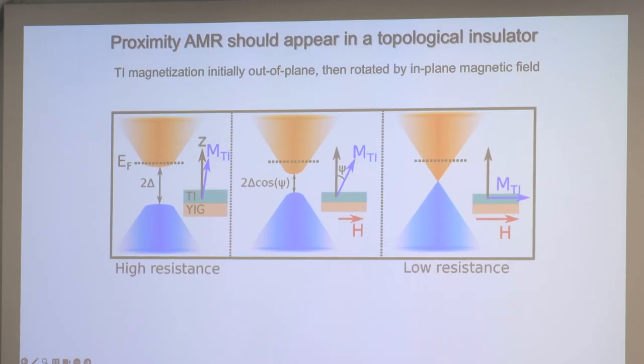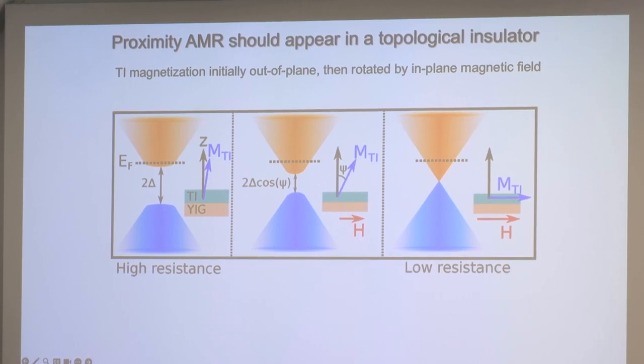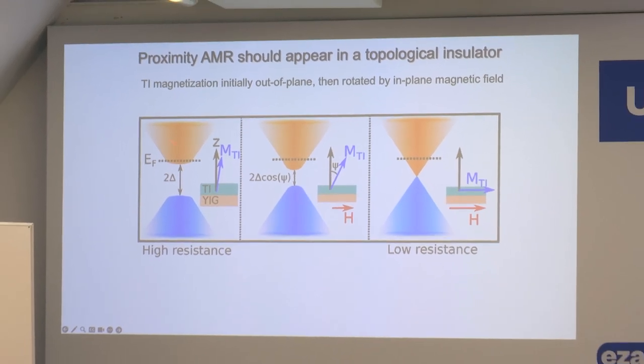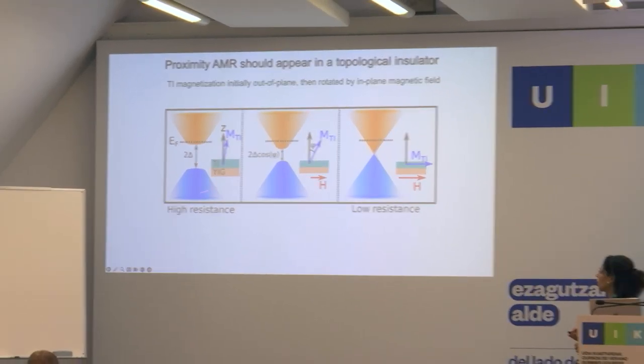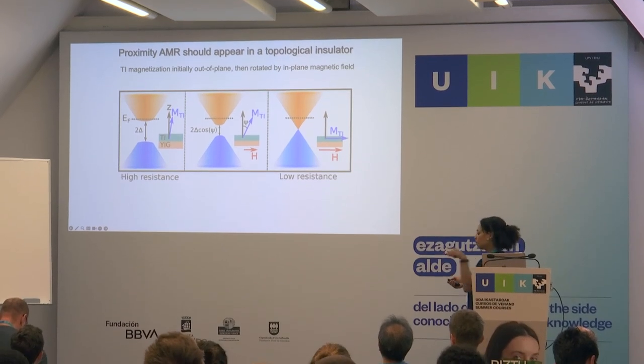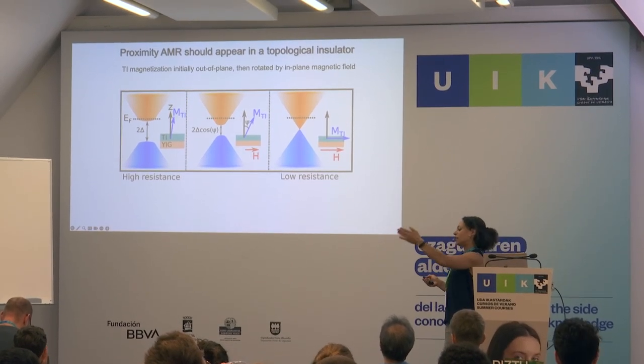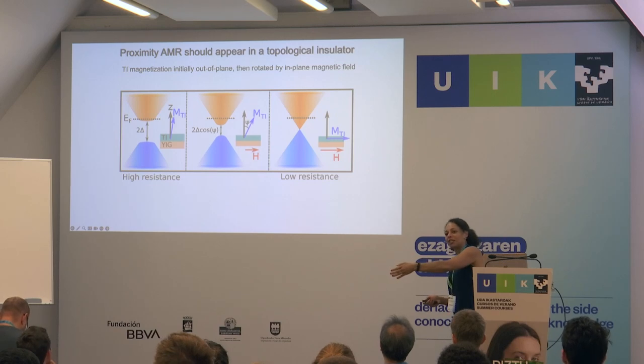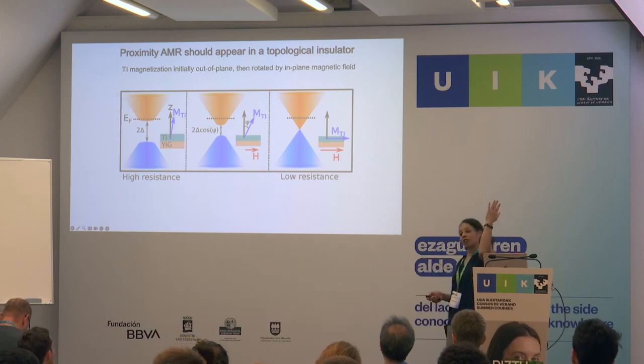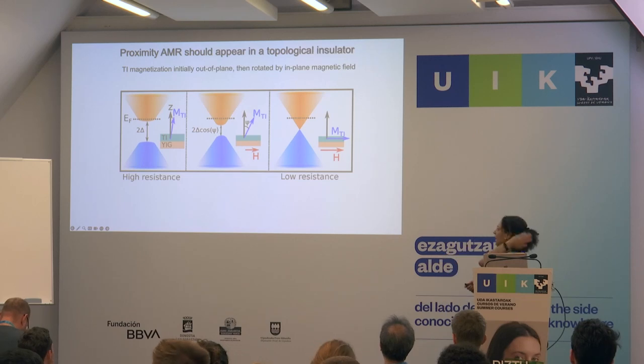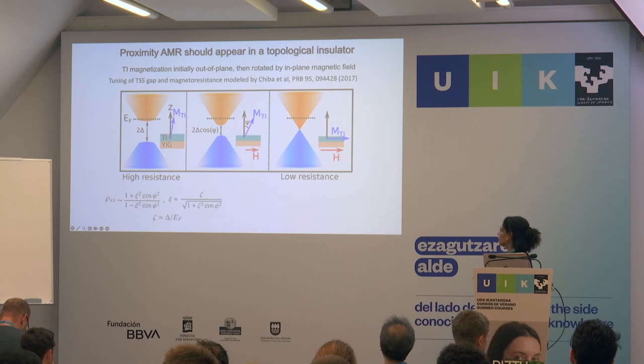Okay. Now, in topological insulators, you should also see an AMR, but it should be different from the standard type of AMR. In this case, what you should see is in the gap state, when you have a magnetic field that's out of plane, for example, you should have a gap, and this should give you a high resistance state. Now, if you apply an in-plane field then, it should rotate the magnetization and close the gap. Because for a topological material, you expect the gap for an out-of-plane field, but not for an in-plane field. And so as you close the gap, you should go from high resistance to low resistance, going from an out-of-plane to an in-plane field. And so this has been modeled before.